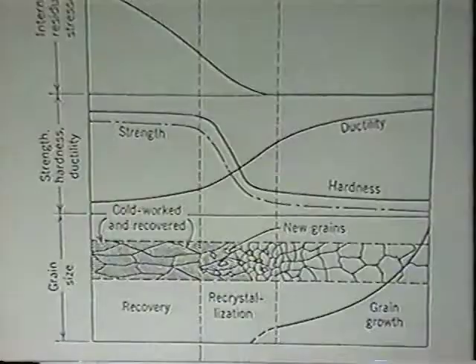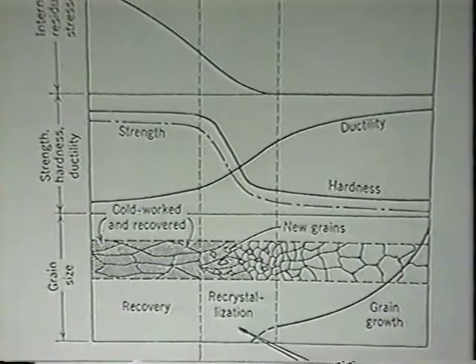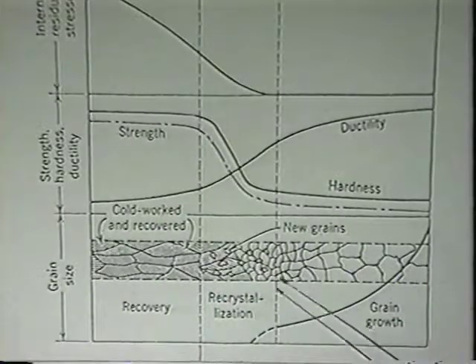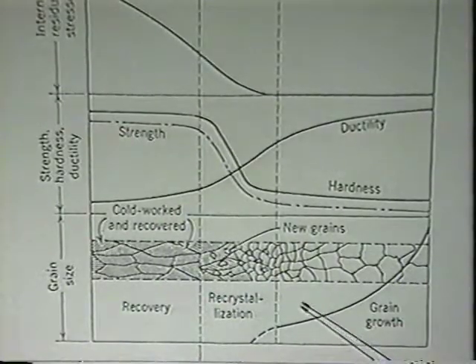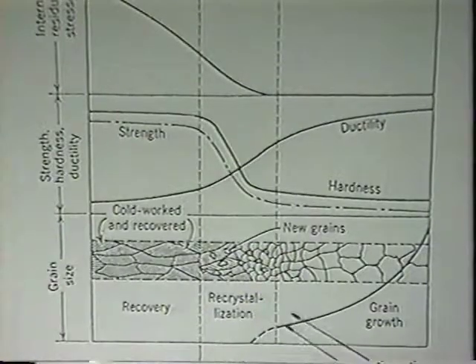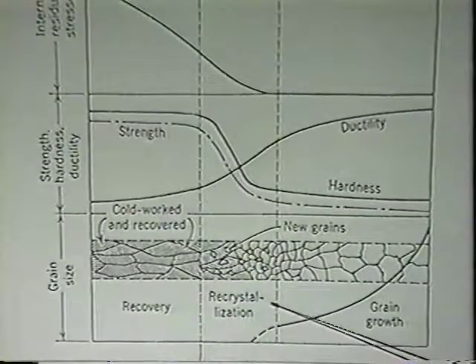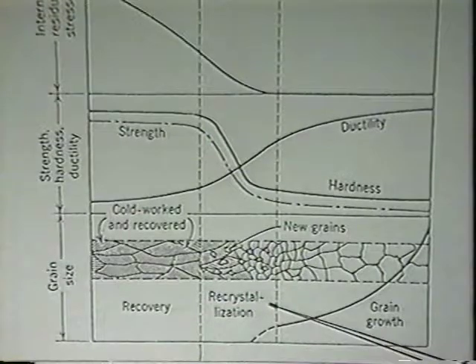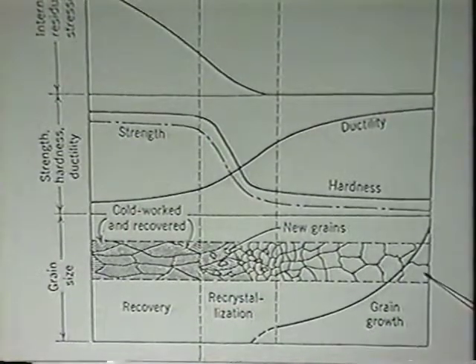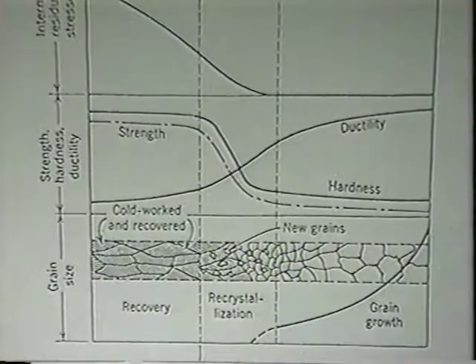Depending upon which products you purchase, we'll produce them through the anneal cycles here. Now, there are some chemistry issues too, but basically this is where we're making the strength issues. And those are CQ, DQ, DQSK, EDDQ. It's important to know that. And this is time. Recrystallization in the batch anneal is 3 days. To get this grain growth, we're talking 5 and 6 days. So now you can start to appreciate some of the cost differences between a DQ and a CQ and a DDQ.